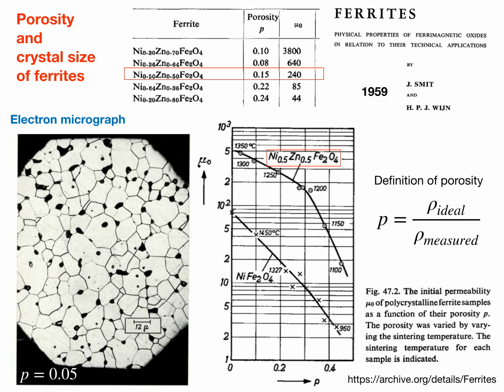In order to compare measured permeabilities, it is important to consider the porosity. For example, for the material considered here, which is a 50-50 nickel-zinc ferrite, an initial permeability of 240 is quoted for a porosity of 0.15. These values and the micrograph are from a standard book on ferrites from 1959 by Smit and Wijn.